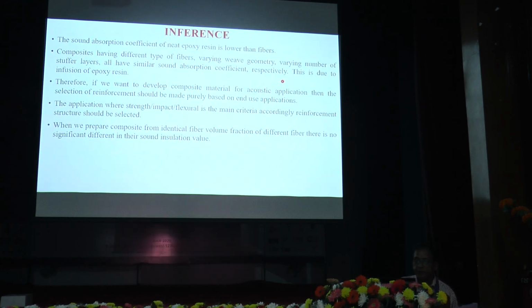Therefore, we have to develop the composite material specifically for acoustic applications. The selection of reinforcement should be made purely based on end use, where strength, impact, and flexural characteristics are the main criteria of the reinforcement structure. When preparing the composite, identical fiber volume fraction should be maintained, and there is no significant difference in the sound insulation value.